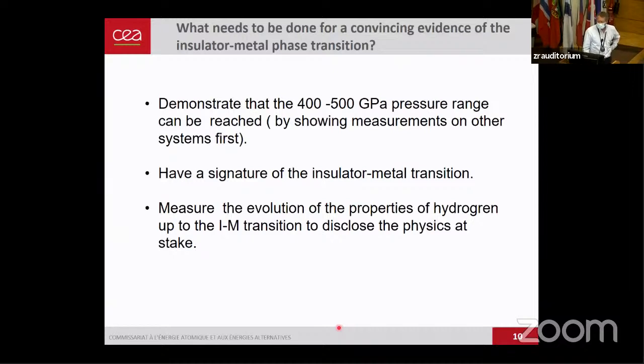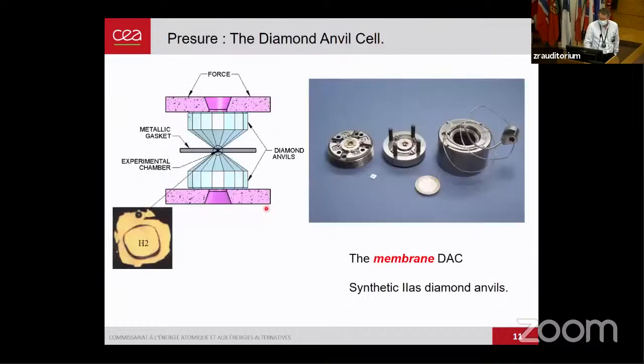So what needs to be done to provide convincing evidence for the insulator-metal phase transition? First, we have to demonstrate that we can do measurements in the 400 to 500 GPa pressure range, 4 to 5 million atmospheres. That is above what has really been done by the static pressure community. And we have to do that on other systems before claiming it on hydrogen. We have to have a signature of the insulator-metal phase transition. And we have to measure the evolution of the properties of hydrogen until it reaches metallization, so that we can understand the physics at stake and compare with calculation.